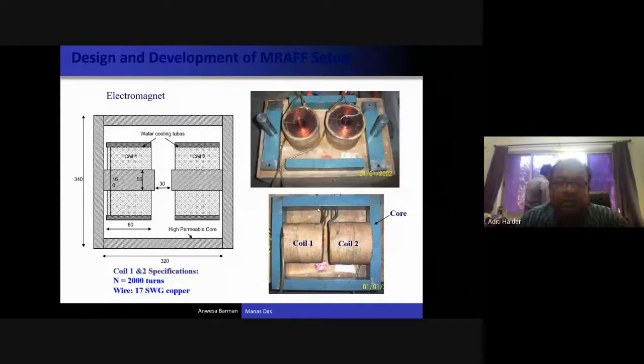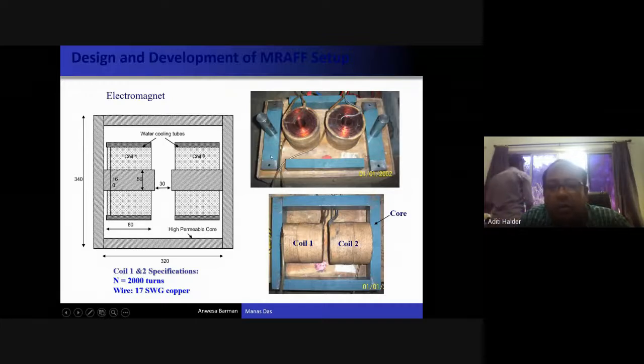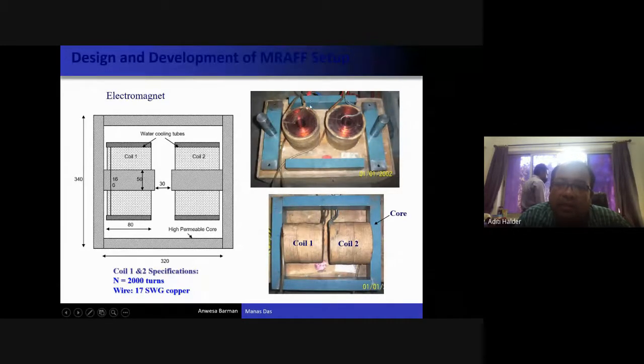Yes, sir. Actually, this is the electromagnet we are using here. There is a core material, and this is the coil here. It is called a C-type electromagnet. Instead of using this cold rolled annealed steel, you can use low carbon steel. And on this coil you can see outside there is a cooling channel. It is a copper channel, through which chilled water flows over the copper coil, so that whatever heat is generated can be removed. So this electromagnet you can use for 1 to 1.5 hours, and it can work perfectly without any damage to the insulation of the copper wire.